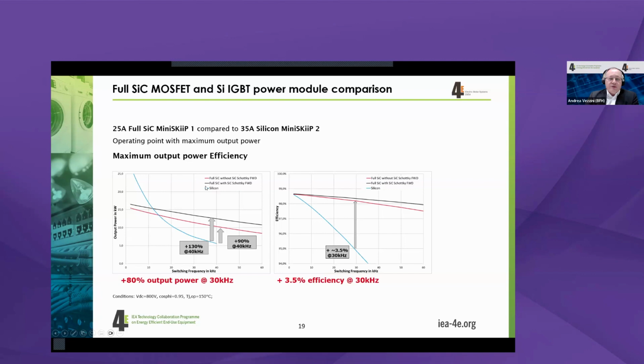When you look now at full SiC, the red line is without the diode, the black line is with the freewheeling diode. As you can see, it's a better performance. And as we see, the impact of the switching losses is much less. And especially, as you can see, at higher frequency, we have an advantage of the silicon carbide modules. This advantage on total output power, for a given loss amount, is translated directly into efficiencies.